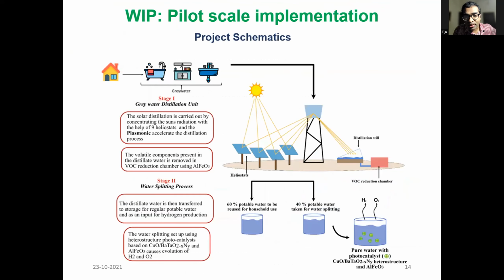So currently, it turns out that on the roof of MPS, these materials are being tested. We are setting up a pilot plant for testing these materials. So not only will we be using sunlight, but we'll be actually using heliostats to get concentrated solar power. And the eventual goal is to start with something like gray water, the kind that comes out of your kitchens, for instance, to get potable distilled water by using plasmonic distillation on one hand. And prior to going there, trying to make sure that we use our aluminum ferrites and so on in order to make sure that the organic pollutants are gotten rid of.